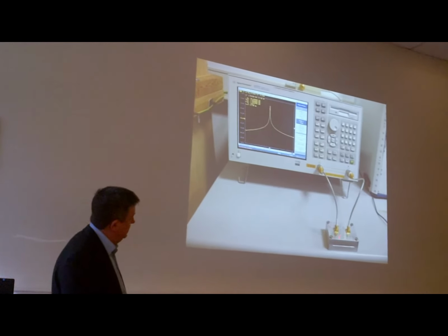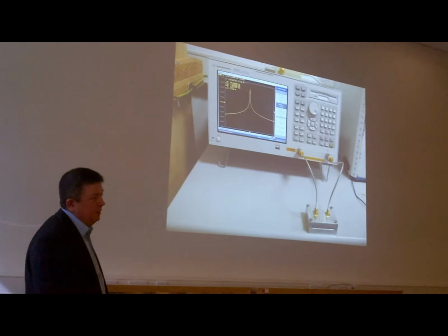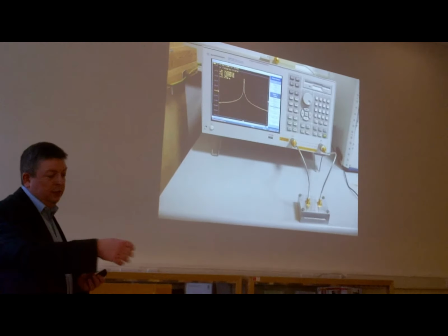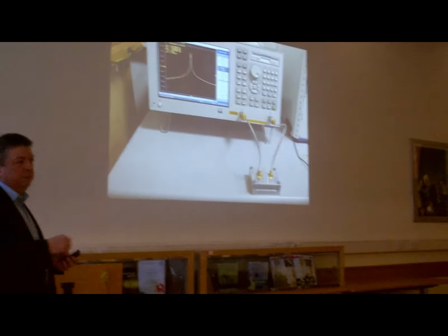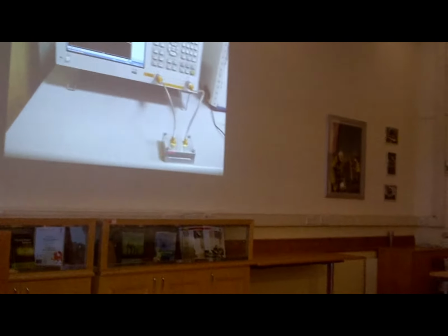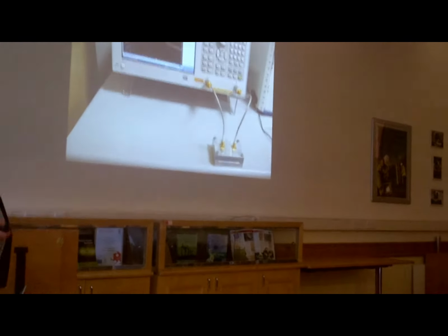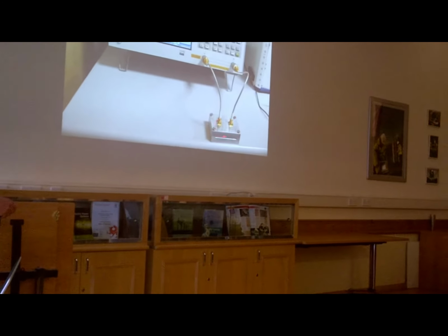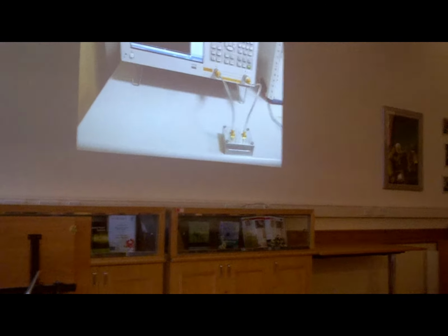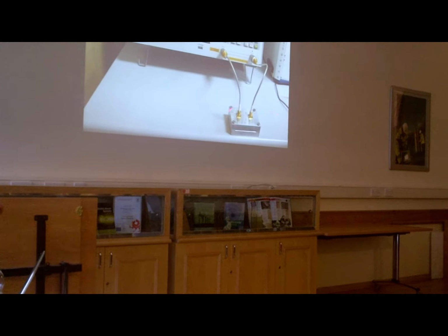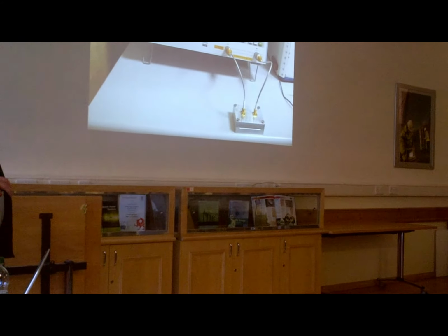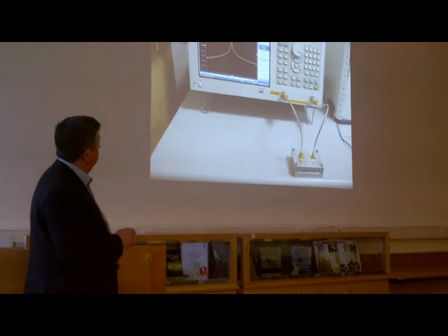And this little cavity here has a dielectric resonator in there. And for this particular application, you paint on a card the pigment that you're interested in, and you slot it into this as you would a credit card. And then this looks at microwave absorption in addition to microwave polarization, and hence they use this as a quality control mechanism now in the production of their pigments in Darmstadt.